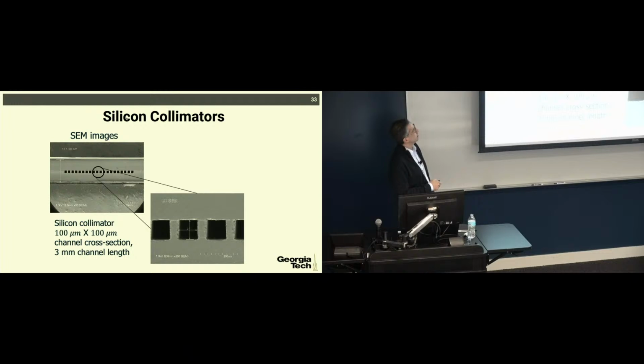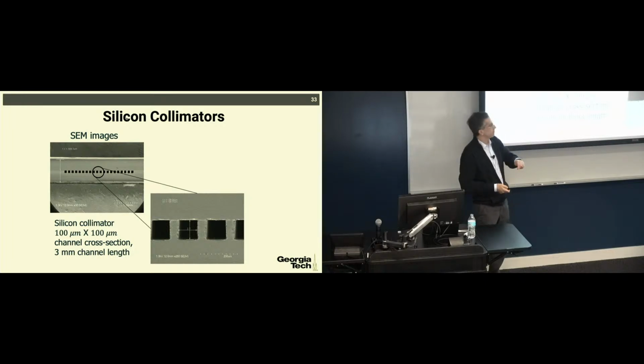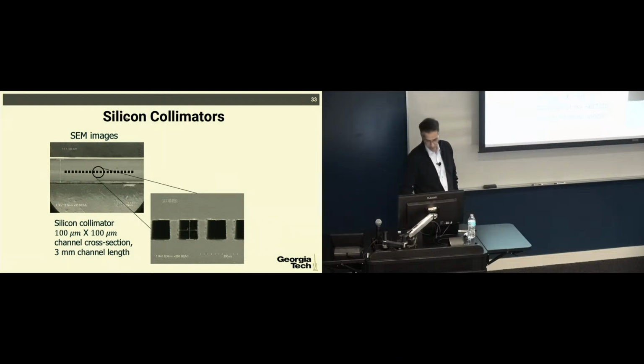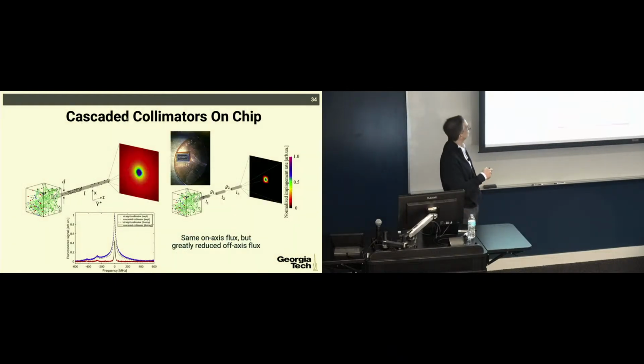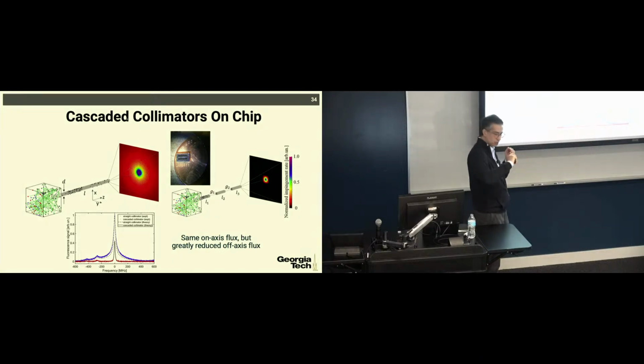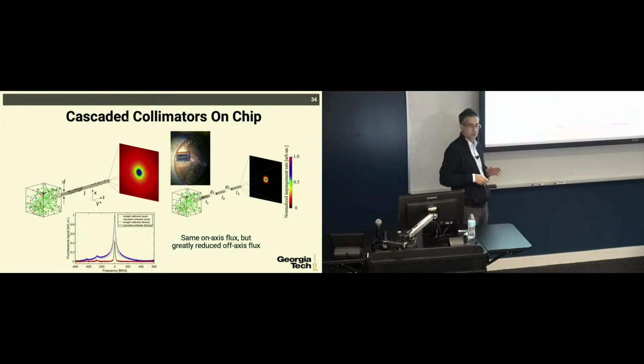These silicon collimators are pretty neat. We etched channels into silicon using deep RIE. We can easily control the dimensions. Then you bond another wafer on top of it to create these buried channels, and these buried channels can be used as the collimators that I mentioned. If you put a bunch of rubidium atoms here and run them through that collimator, you would see that they all get collimated. This blue line shows you that all the rubidium atoms are being shot from those channels in a straight line, which is ideal for all sorts of sensing applications.